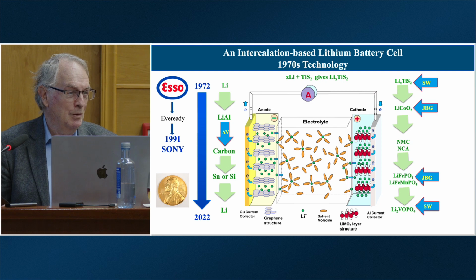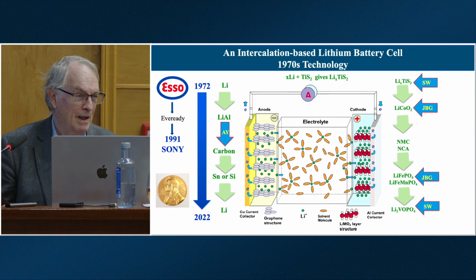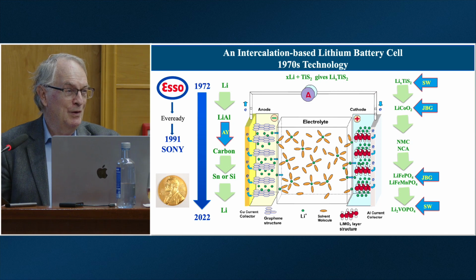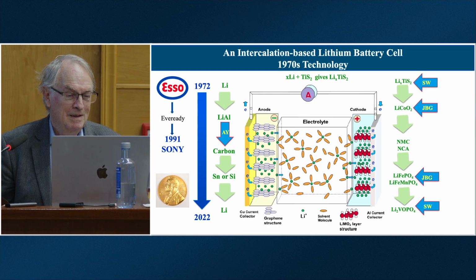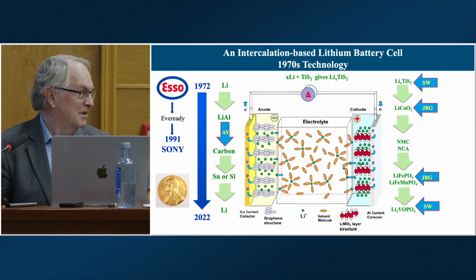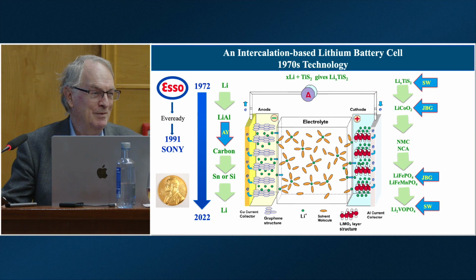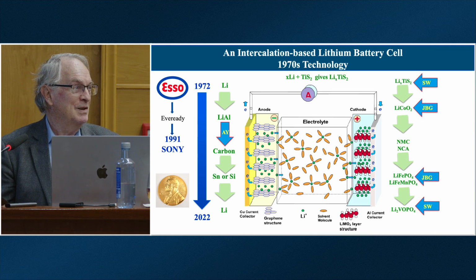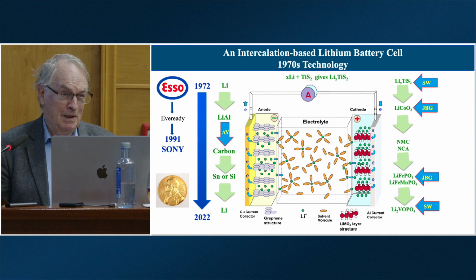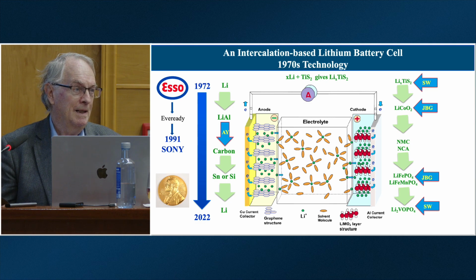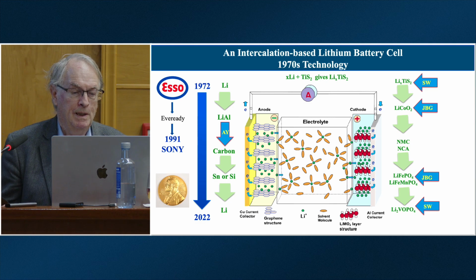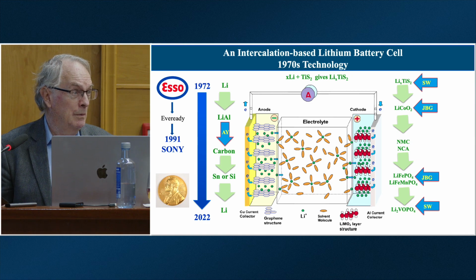Well, no self-respecting chemist would ever try it. If you took lithium out of lithium cobalt oxide, you land up with cobalt 4+. But if you read all the textbooks, cobalt 4+ doesn't exist. So why even try it? I think these days we know we can make what we call metastable compounds, which you cannot make by normal high temperature methods. So he tried it, it works very well.